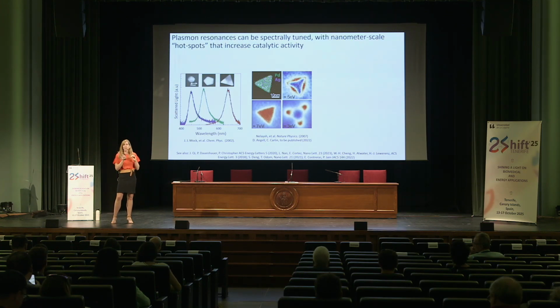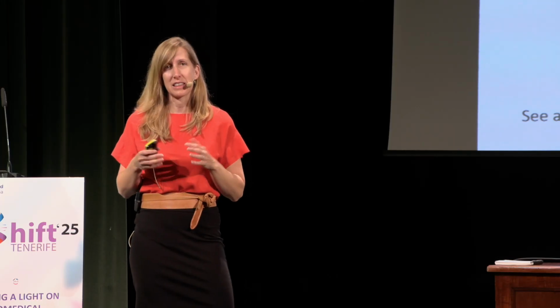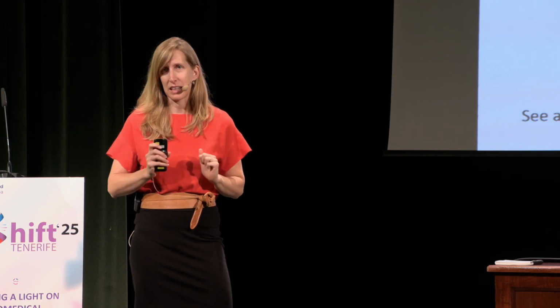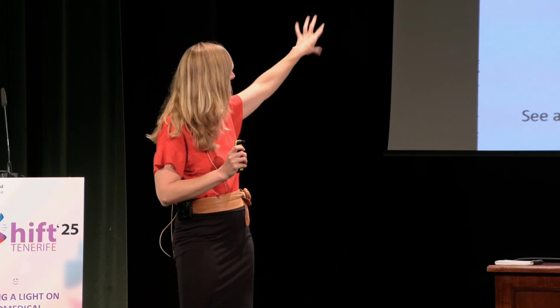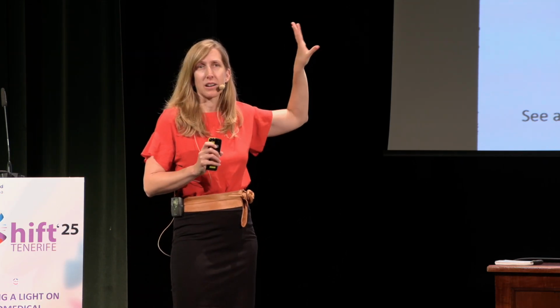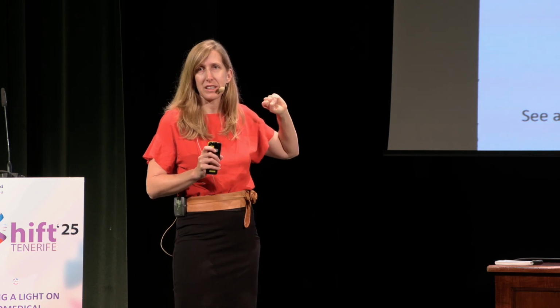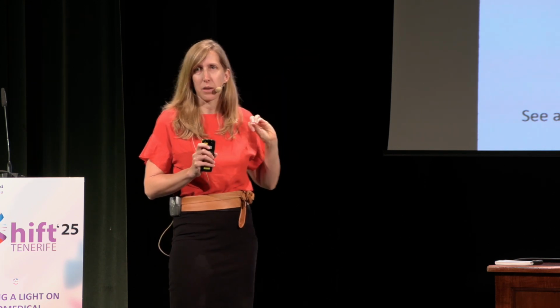And then if you go in with an electron microscope, you can actually probe how light is being controlled on a length scale that's comparable to the metallic nanoparticles. So here is actually an industrial catalyst that's used for creating ethylene. It's silver plus palladium. And you can see that the silver and palladium are alloyed together almost homogeneously, so we can figure out the elemental composition.